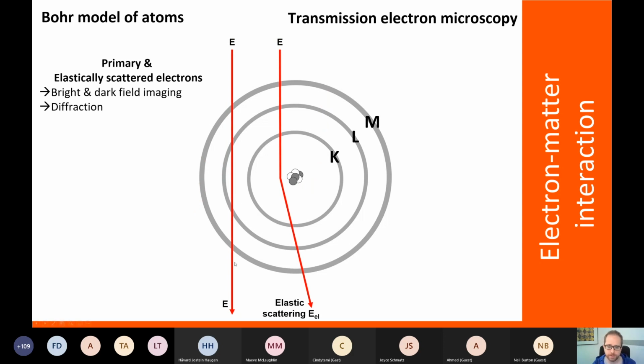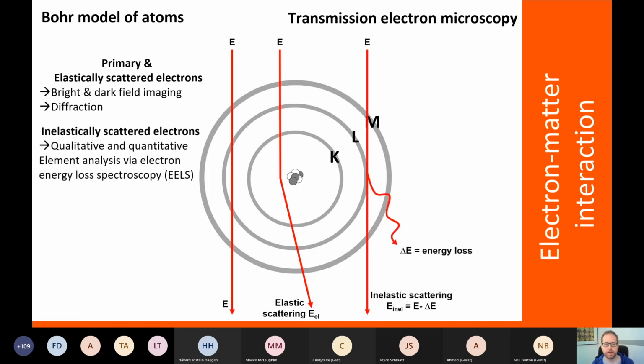So we have a beam that goes straight through the sample and is not interacting with our material at all, or we have electrons that go through our sample, interact with the nucleus, and are elastically scattered. That means they change their path. So here we see this represented in this little kink. With elastically scattered electrons, we can do different types of imaging. We will, in later lectures, in more advanced courses, talk about specific bright field and dark field imaging. We can use it to do diffraction as well. And diffraction in a TEM will be a specific lecture later today.